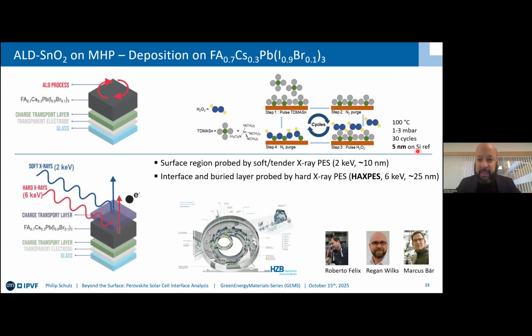You then take the film and probe this by XPS and HAXPES, so soft and tender XPS, in order to measure the first 10 nanometers at 2 keV. And then the interface and buried layer probed by hard X-ray photoemission spectroscopy via HAXPES, going down to 25 nanometers in the subsurface region. We did all this for this and the next example that I will show at synchrotron BESSY, together with a team of Marcus Bär and Regan Wilks, the beamline scientist Roberto from the HIKE end station and KMC-1 beamline at HZB.